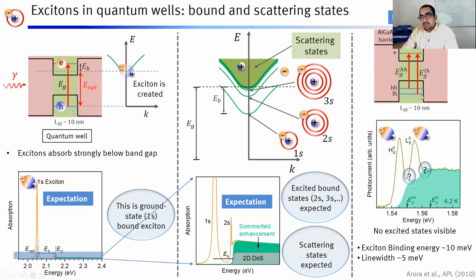So this is this gallium arsenide quantum well. And then there are two types of hole levels present in this gallium arsenide quantum well. These are called heavy holes and light holes. Actually, these come into picture due to the hybridization of p orbitals, which make the valence band. And then you have one of the holes which has a larger effective mass than the other. So this is why that's called a heavy hole. So you can have two types of resonances called heavy hole exciton and light hole exciton.